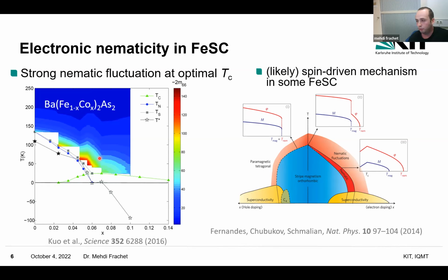So now the question that follows is, what is the mechanism behind this electronic nematicity? The consensus, or most evidence, points to a spin-driven mechanism, at least in some iron-based superconductors. One manifestation of this is the proximity of the long-range magnetic order, this stripe magnetism.